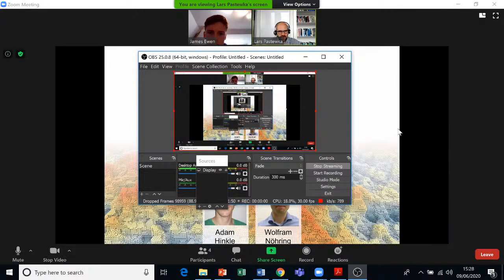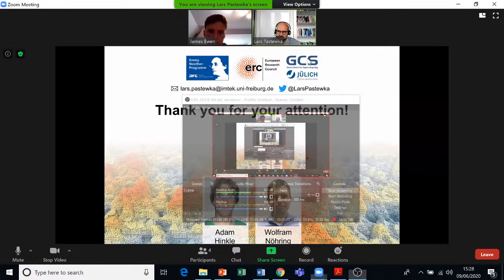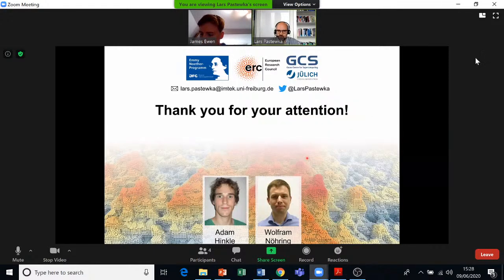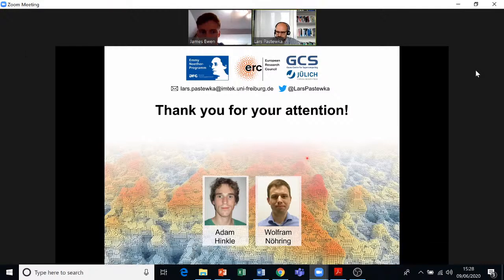So our calculations were initially dislocation free. So we have homogeneous nucleation or nucleation from surfaces. So it's something that we are still looking at. But let me point out that it looks like this is not tied to dislocations. I mean, this was part of the exercise of using this glass structure, to have a material that has a completely different mechanism of accommodating deformation. That has nothing to do with dislocation. It's shear transformation zones. It's local regions that flip under an external stress.